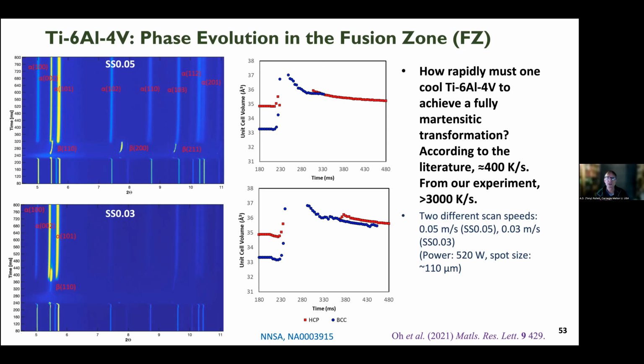And crucially, the key difference that we found was that the cooling rate required to have it be fully martensitic is quite a bit higher than reported in the literature. And that's very useful information, because if you're going to be able to take the process conditions and use those to predict microstructure and properties, this is information that you have to have. Okay, so I reckon I have about 3 minutes left.